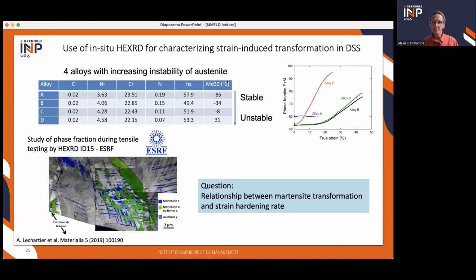And so this system is duplex stainless steels, DSS, and these were more or less at 50%. Well, we tried to have 50% alpha and gamma in 4 different materials, but by playing especially on the nitrogen content to have a different stability of the austenite, which means a different stability with respect to deformation. So in alloy A here, it's very stable. You have the phase fraction in situ measured by X-ray diffraction is constant with strain. Whereas in alloy D, you have almost a full transformation of the austenite into martensite. And in alloys B and C, it's kind of intermediate.